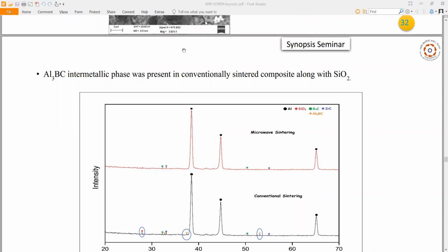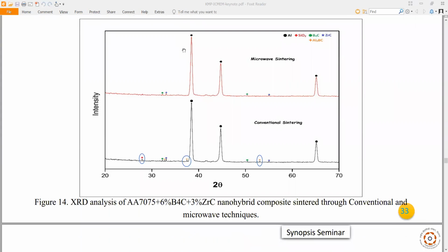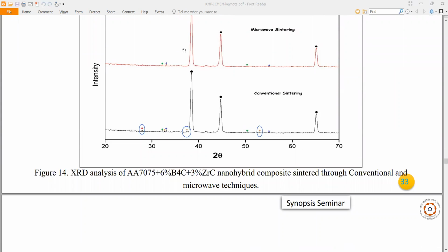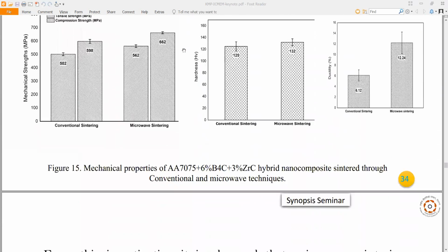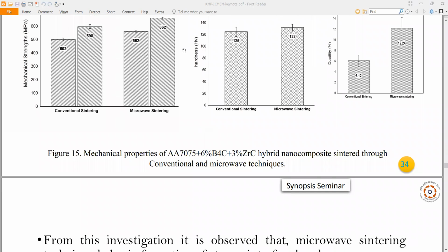Then Al3BC intermetallic phase was present in conventional sintered composite along with silicon dioxide. So this is the diagram and this is figure 14. This is XRD analysis of AA7075 plus 6% B4C plus 3% zirconium carbide nanohybrid composite sintered through conventional and microwave techniques. Then this is figure 15, and this shows mechanical properties of AA7075 plus 6% B4C and 3% ZrC hybrid nanocomposites sintered through conventional and microwave techniques.